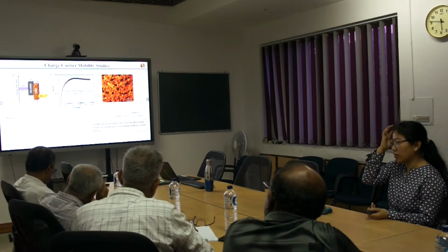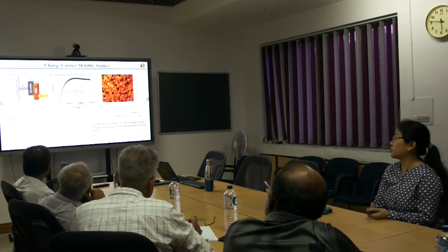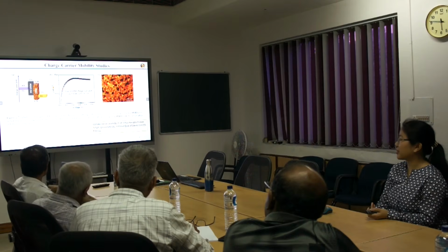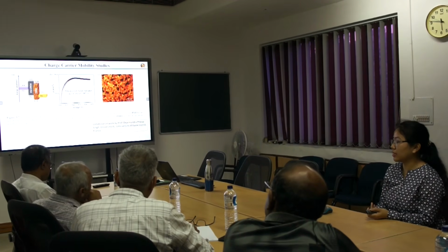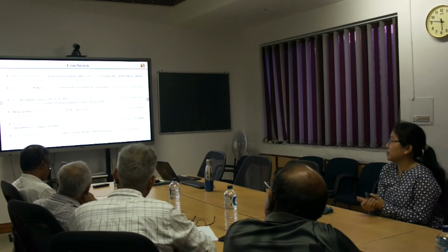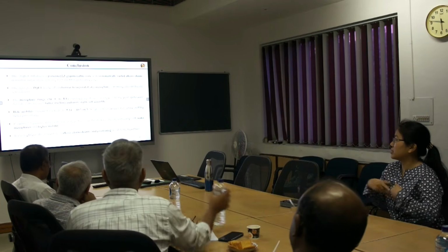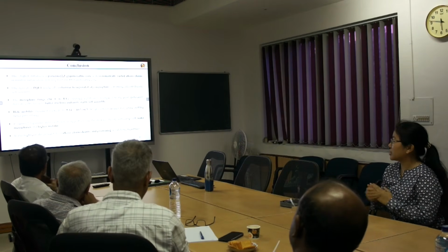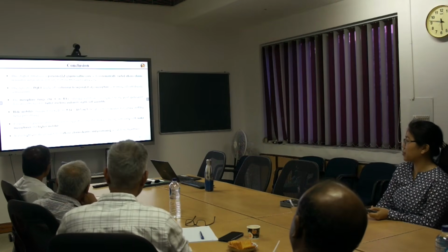So we can observe an improvement from the phenanthrene-based molecule: the hole mobility increased markedly from 10 to the power minus 6 in the previous chapter to 10 to the power minus 4 in the pyrazine phenanthrene. So in this chapter, we introduced pyrazine phenanthrene where we varied the alkoxy chain, and one derivative, PQE1, showed a hexagonal phase at a certain temperature.